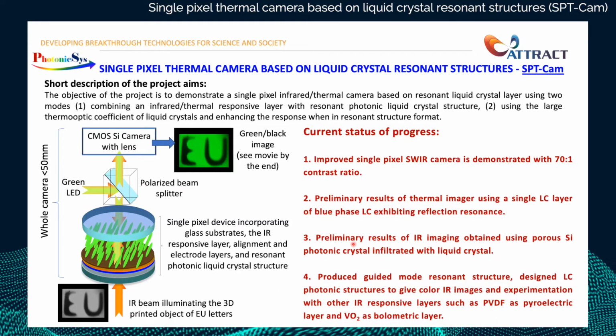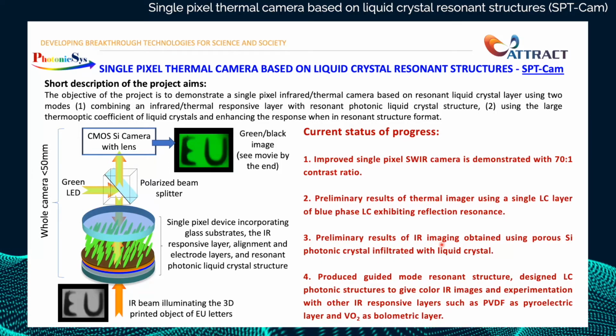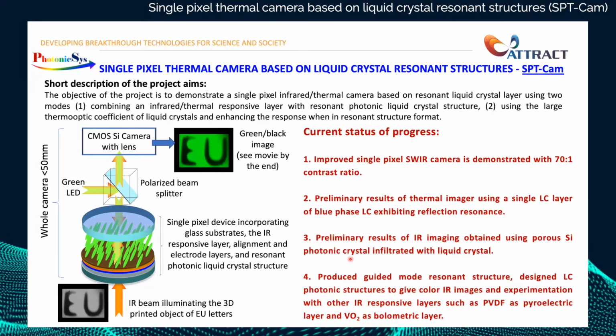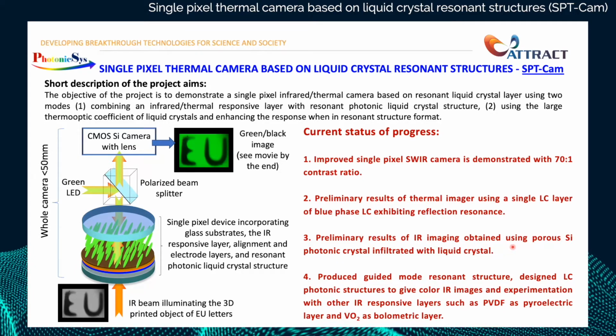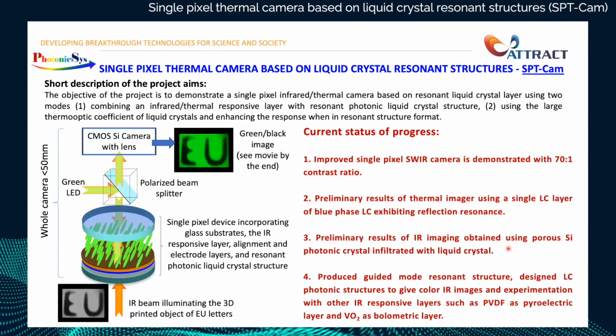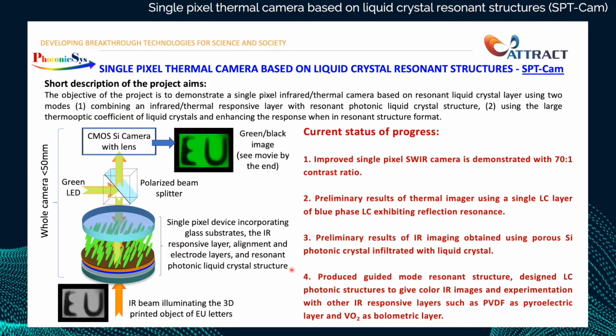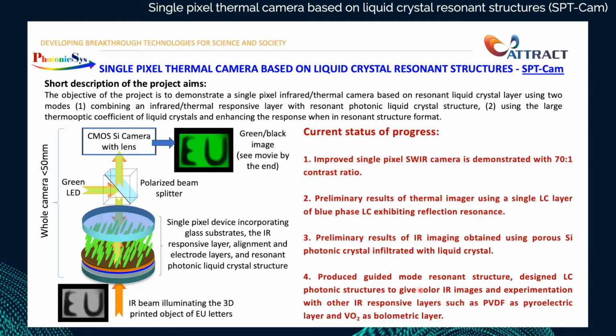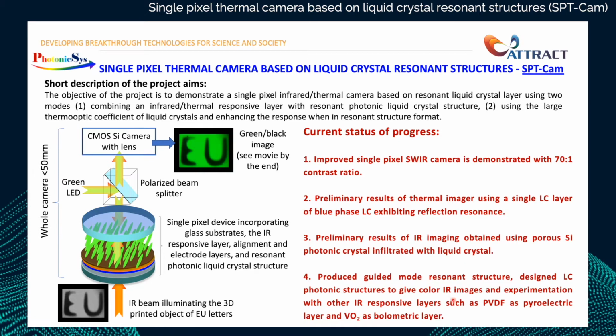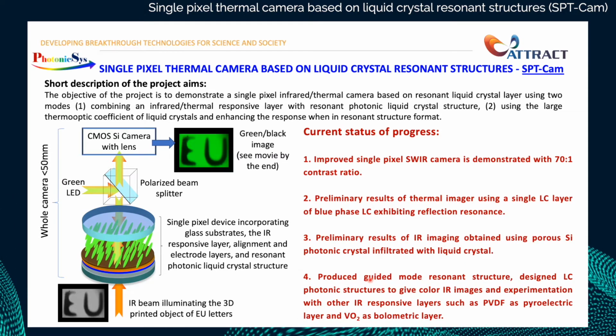We also have some preliminary results using porous silicon photonic crystal infiltrated with a liquid crystal layer, and it shows resonant peaks. These resonance peaks are sensitive to the temperature variations. We did a lot of experiments also using other resonant structures like Fabry-Perot type, guided mode resonance, and how to produce them so that they become uniform and in a cost-effective manner, like glass etching, lithography, and so on.